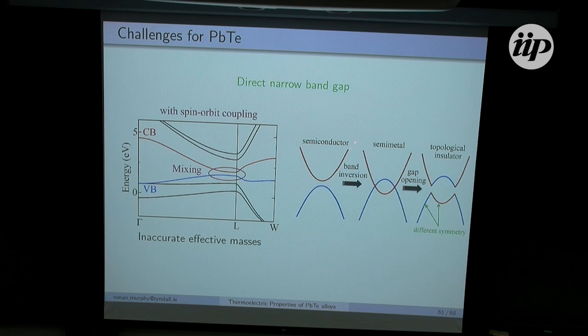Just to talk briefly about that last point. This is a DFT calculation. DFT, as it turns out, is actually underestimating our band gap. This leads to a situation where we have a crossover of the conduction and the valence bands here.